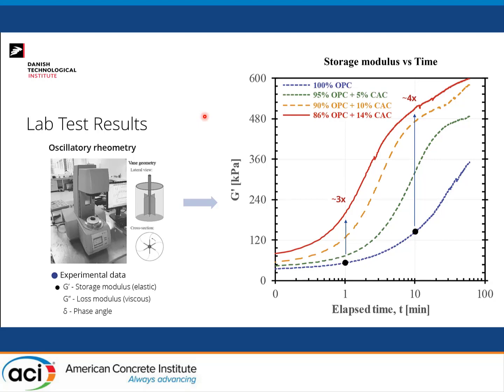And I won't go through a ton of the results we got. I just want to highlight the effect, only on G prime now; there's a lot more data and this could be shared in different publications. So I want to highlight what happens when we add this calcium aluminate slurry as an activating ingredient. The bottom curve is the one with pure white Portland cement, I'm just putting it as OPC here. So I have an evolution of G prime over time.